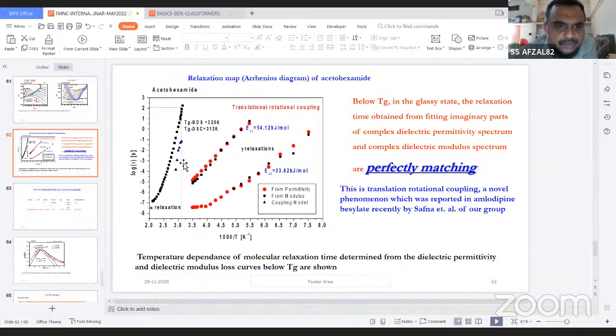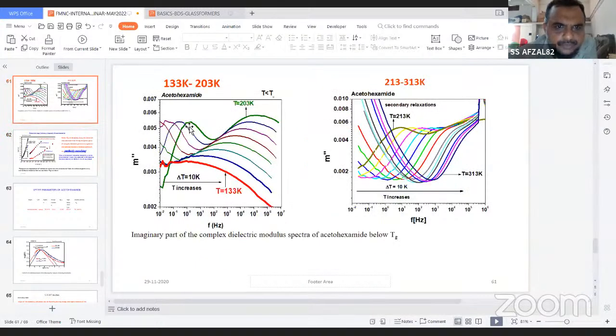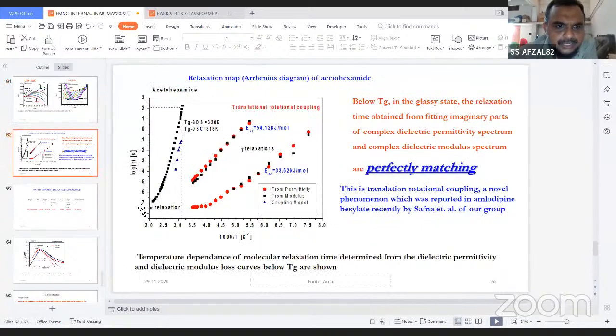So after that, what we do is we will plot an Arrhenius graph, that is nothing but the log tau. That is, as I told you, from the peak of this, we get the frequency and then we get the time. That is the time of the relaxation, and then we convert it into log tau. So that is plotted in the y-axis. And then the corresponding temperature is taken in the reciprocal, 1000 by T is plotted in the x-axis. So the use of this is we will understand the temperature evolution of the relaxation process.